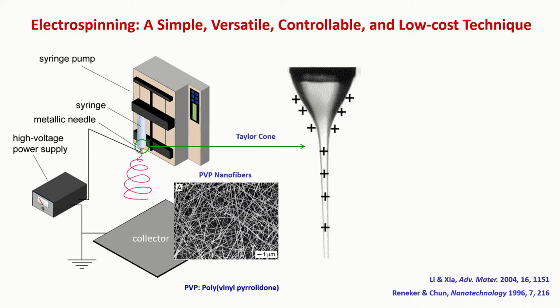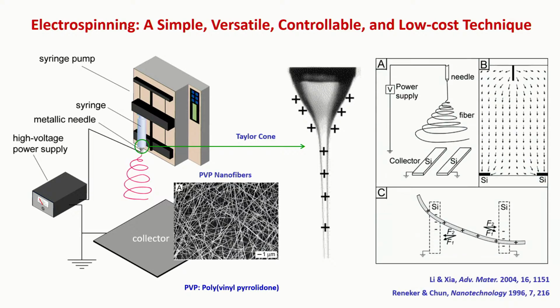It's a very broad size range. So you can control the voltage used, polymer weight, molecular weight, the polymer concentration, and many other parameters. You can have very good control over the diameter of these nanofibers. And specifically, quite a long time ago, we found that we can also have these fibers aligned, rather than have this random morphology.